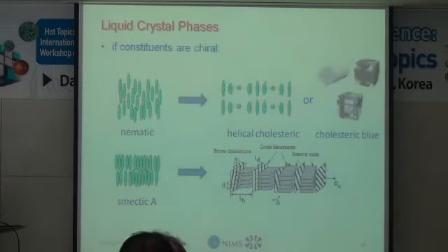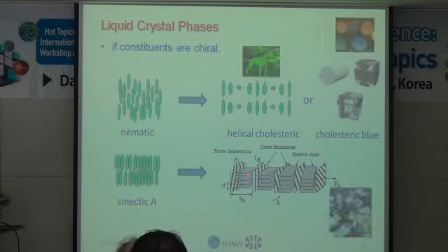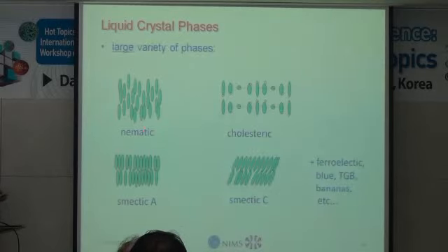Now, the materials may be chiral, so they can be handed, left or right-handed. And then one can get other interesting phases. One can get phases where the direction of average orientation rotates in space. So these are helical cholesterics, or there are these exotic cholesteric blue phases that are made up of these cylinders where there's twist in all directions as you move away from the axis, and then these cylinders stack in various configurations to be nearly space-filling. Smectics also form interesting chiral structures. So the bottom line is that there are many, many phases in addition to these two simple ones with increasing complexity, and I think there are still new phases that are being discovered.